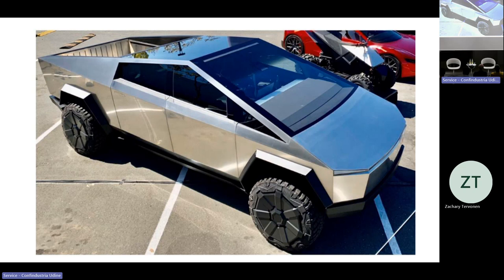But the real story is that, if you have sheet which is 3 millimeters thick and 2 gigapascals strong, you cannot form it into the sort of curves that you have in normal cars. You can bend it, all right? And that is the reason for this shape. But nobody knows, they don't publicize that fact. Now, the advantage also is that you don't need any forming presses. The bending equipment is much, much easier. So this costs $100,000, and people buy it.